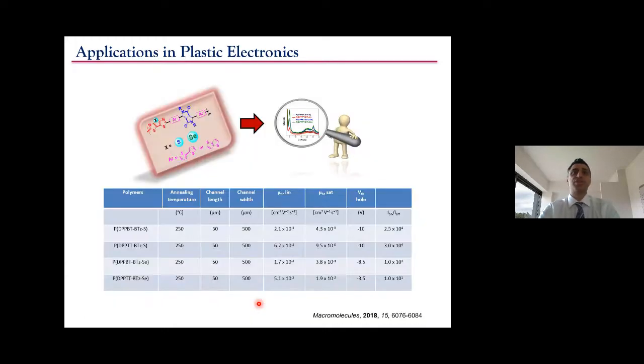We were also interested not only to see if thiazole had an effect, but can we change a heteroatom? For example, as we know, sulfur is naturally also available. Garlic contains a lot of sulfur. Can we change the carbon or nitrogen to sulfur and to selenium, modify the ring system and get mobilities? And also this work was published in Macromolecules, which showed good mobilities for these materials.